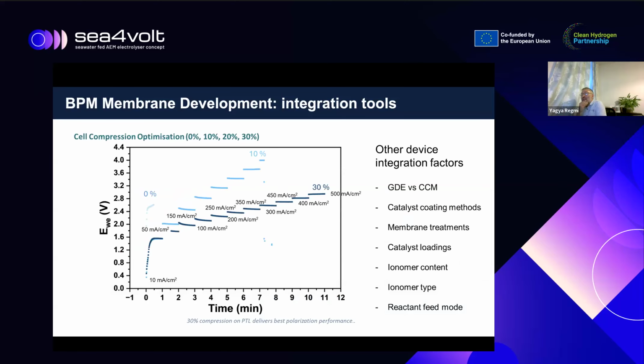The other thing that I want to highlight here is just selecting the right component is not the only knob you can turn in these things. There are different ways. The way you integrate your component into your cell, the way you run the cell. For example, this is well known in electrolysis area, but I just want to highlight. Just like in PEM or AEM electrolyzers, the cell compression makes a huge difference. What you are seeing in the graph is the one that said 0% has no, the MEA, membrane electrode assembly, is not compressed by using different gasket thickness versus your MEA thickness. By the time you go from 0% to 10% compression, performance increases by a lot. And the optimal cell compression we found was 30% compression.